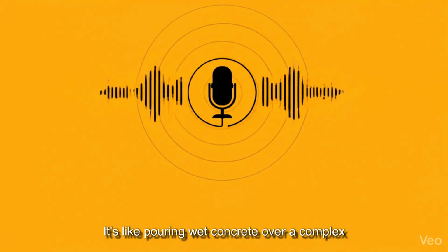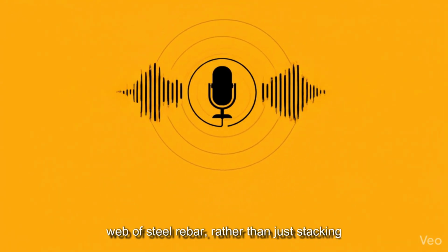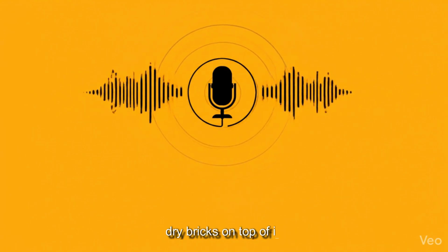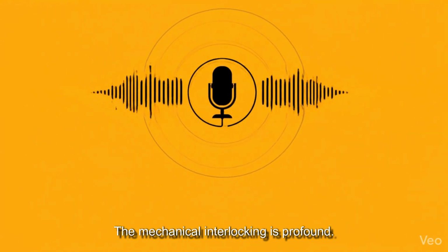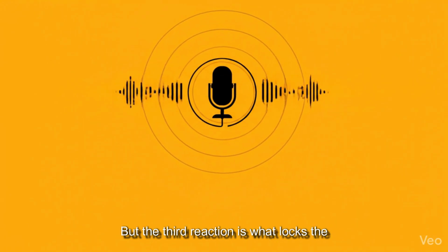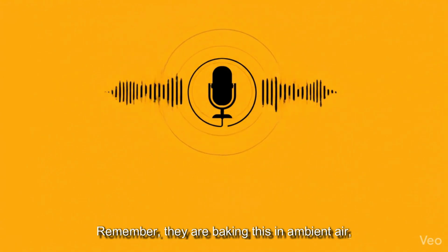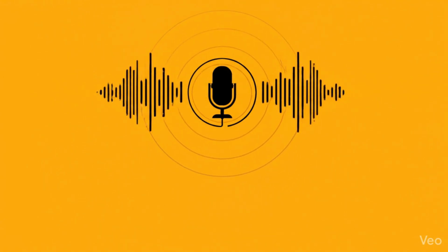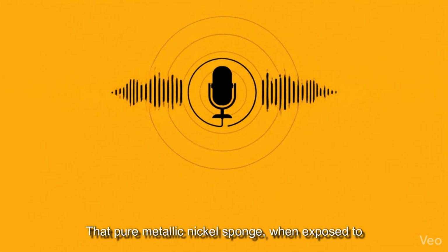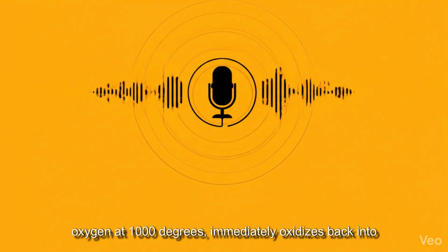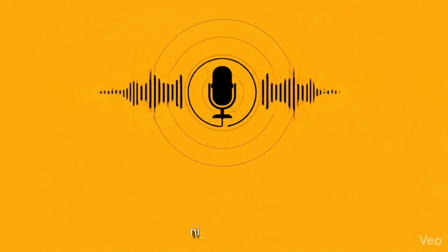It's like pouring wet concrete over a complex web of steel rebar rather than just stacking dry bricks on top of it. The mechanical interlocking is profound. But the third reaction is what locks the trap. Remember, they are baking this in ambient air, which is full of oxygen. Okay, yes. That pure metallic nickel sponge, when exposed to oxygen at 1,000 degrees, immediately oxidizes back into nickel oxide.